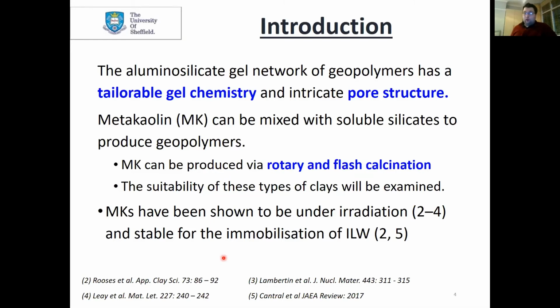We've been able to do that with metakaolin-based geopolymers. Metakaolin can be produced by rotary and flash calcination methods. What we're going to do here is examine the suitability of these materials under irradiation - we're going to irradiate these metakaolin-based geopolymers and see what happens.